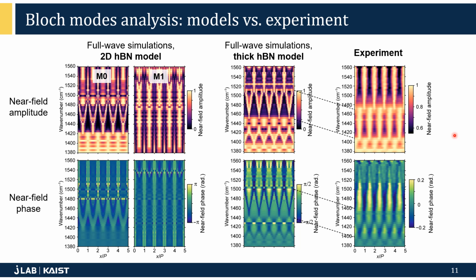The measured hyperspectral near-field maps show the characteristic pattern of the first order mode in both amplitude and phase. This is in perfect agreement with theoretical expectations, as only the first order mode is strongly modulated and the higher order modes are suppressed due to the absence of scattering. However, it is difficult to observe the predicted existence of the first order mode's bandgap in the near-field images above quasi-infinite structure where polaritonic fringes are not visible. Therefore, we also did near-field imaging of the hBN edge.